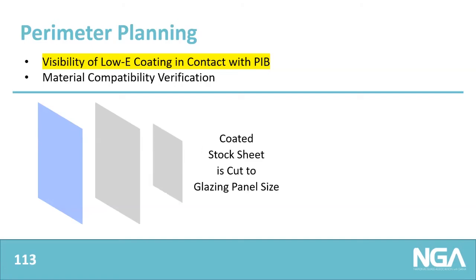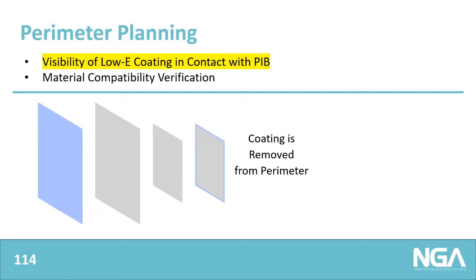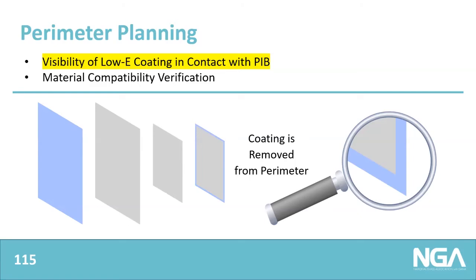The stock sheet is sold to a fabricator. They cut it to size. And then the fabricator would conduct edge deletion, meaning that they remove the coating from the perimeter of the final glazing panel. We see a blow up there, and that perimeter removal is known as edge deletion. And edge deletion is performed so we don't have a conductive path that could lead to coating corrosion. And we also want to perform edge deletion to maintain the quality of the hermetic seal of the IG unit.